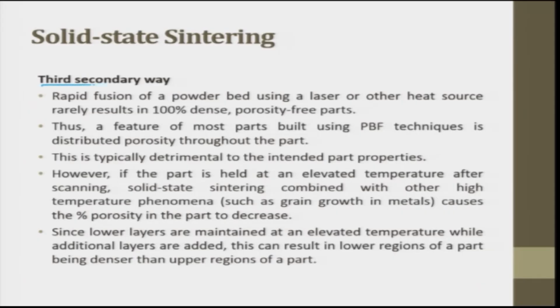The third secondary way: the rapid fusion of the powder bed using a laser or other heating source rarely results in 100% dense, porosity-free parts. Thus, a feature of most parts made using powder bed fusion technique is distributed porosity throughout the part. This is typically detrimental to the intended part property, which is happening inside. However, if the part is held at an elevated temperature after scanning, the solid state sintering combined with the other high temperature phenomena causes the percentage of porosity to decrease.